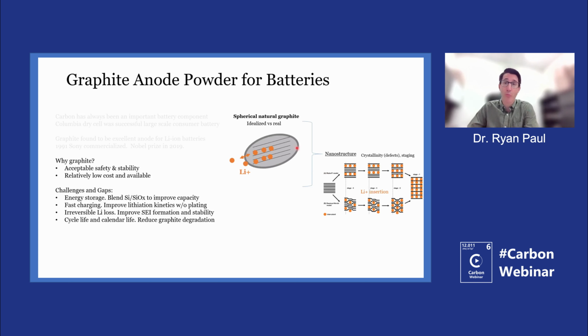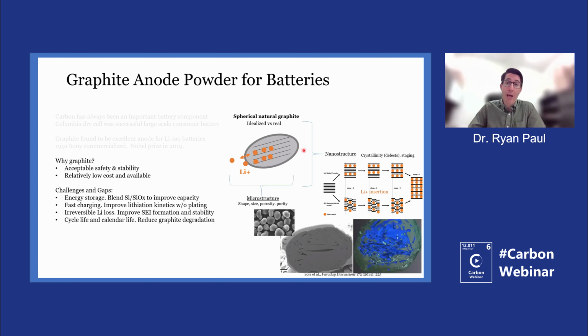But this is a very idealized picture. This is not reality. In reality, graphite particles that are made like this have a macro structure. There's shape and size. There's porosity. And if you think about these graphite potatoes that are made through pounding and shaping of a graphite flake, there is internal porosity in there. And in this paper, they certainly visualize these pore networks using X-ray tomography. So you don't just have this perfect picture here. You have a macro structure, a microstructure, and a nanostructure.